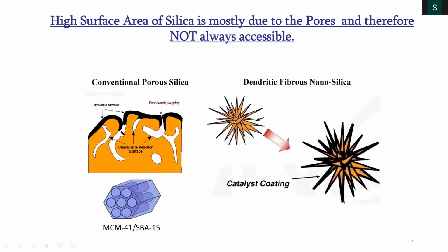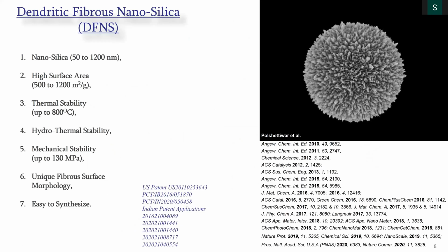So we thought of developing a material which would also have a high surface area, but not due to the pores, but due to something else, for example, due to spikes or fibers. And you can see now these are external surface area, so it's easily accessible. Even if I coat the catalyst, you can see the catalyst is also on the external part of the surface, so it is also easily accessible. So this is what we developed in our lab.